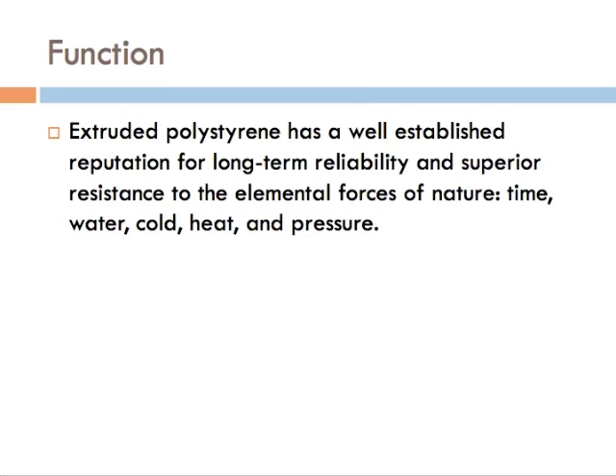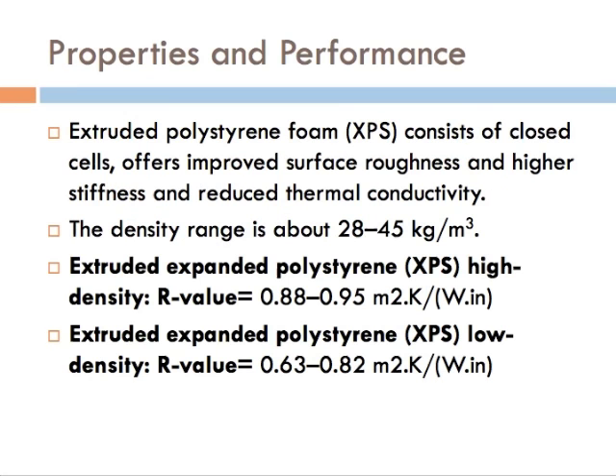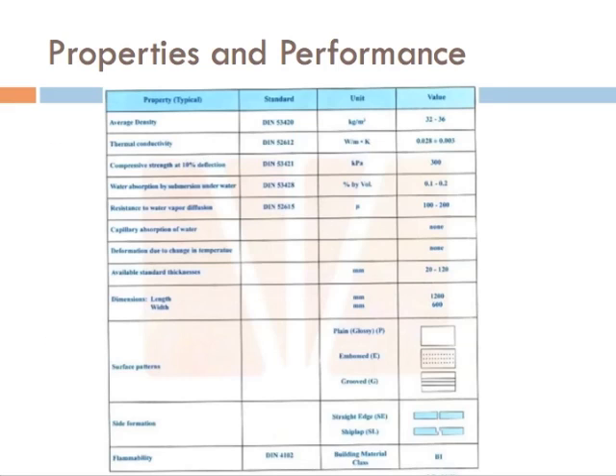It functions to resist not only heat but also cold and water, as well as pressure and wearing due to time. The density of XPS can range from 28 to 45 kilograms per meter cube, and depending on its density, if it is high density, it can have an R value that ranges from 0.88 to 0.95, while low density XPS can have an R value that ranges from 0.63 to 0.82, each being used for its specific purpose. The average density is 32 to 36 kilograms per meter cubed, with thermal conductivity being around